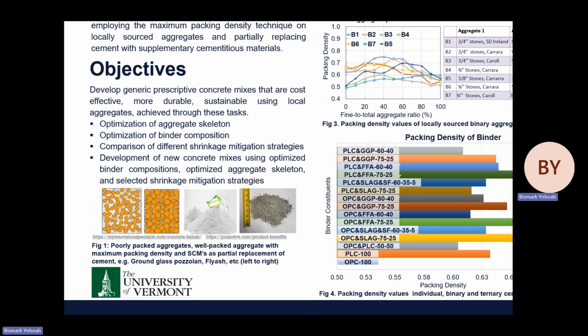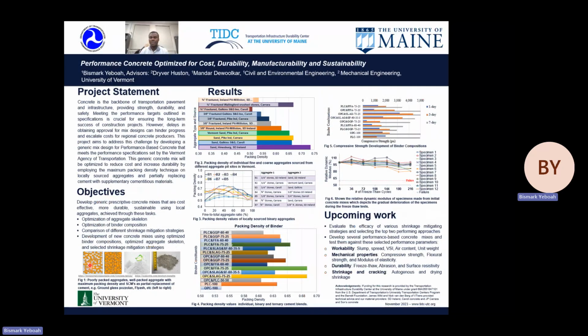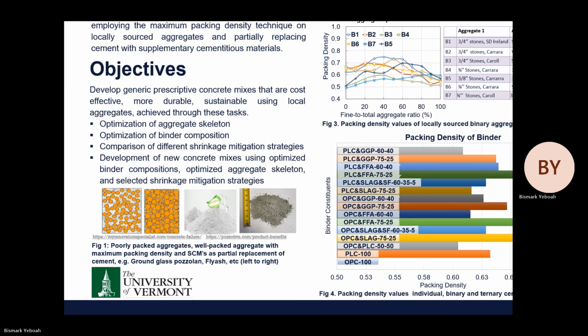So when you look at figure 1 from left to right, the first picture shows poorly packed aggregates. In this case, the void spaces are relatively larger as compared to the second picture. In the second picture, you can see a well-packed aggregate that has been made using packing density to reduce the void spaces, resulting in a relatively smaller volume for the cement or binder to occupy, as we can see here. The cement content of the concrete can also be partially replaced with ground glass pozzolan and fly ash, which are more environmentally friendly supplementary cementitious materials, as seen in the third and fourth picture.